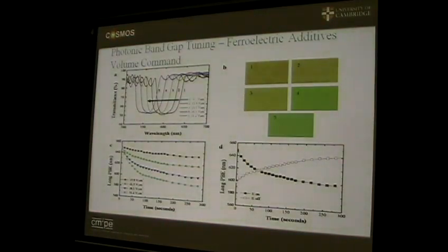The shape of the band gap hasn't changed. So the band gap with zero field and the band gap with the higher field is the same. So your laser efficiency, which depends on the band gap, as I said right at the beginning, isn't altered. So the gain isn't altered. So you've got a switchable system where the gain doesn't change as you switch the band gap.